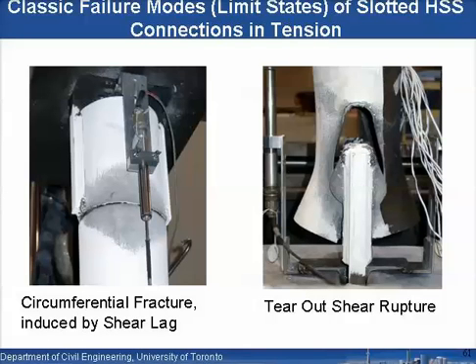So the two key failure modes that I've been talking about are this fracturing of the hollow section around the circumference here, the circumferential fracture, which is induced by shear lag, starting at that little open notch at the end of the slot, or you could actually have shear rupture, where you actually tear out the plate all the way along the sides of the welds here.